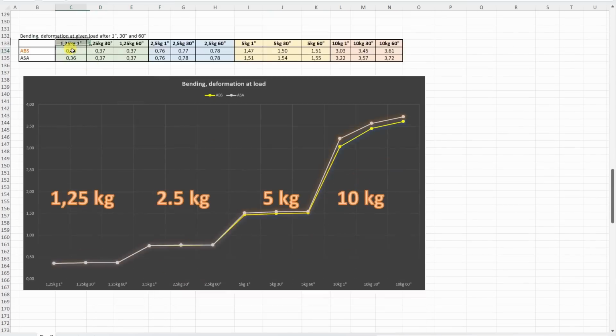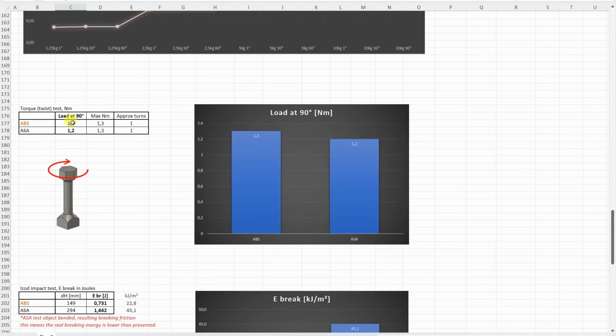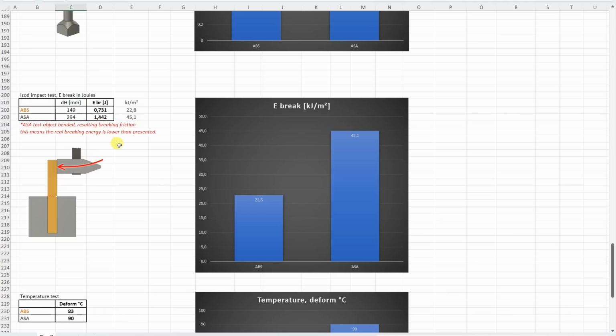This is the deformation under these values after 1, 30 and 60 seconds. And here we can see that at the beginning on lower loads they are almost equal. And then on higher loads actually I could notice a little bit more deformation on ASA material. On torque or twist test, again they were very similar in both cases. On Izod impact test, I already mentioned that the ASA result is deformed because of that additional friction, but this is what I could measure and this data will be added to that summary table, but again with this notification.